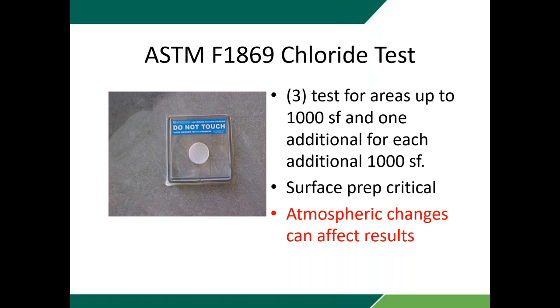This test, again, it's an older test. It's in, I would say, the majority of people's literature. This is where they're getting, when they say 3 pounds per 1,000 square foot, this is the test that they're running to get that. A couple things about the test make it less desirable. One, it requires very good surface prep. If the surface prep isn't done correctly and that dome isn't adhered correctly, you're not going to get the test results to be correct.